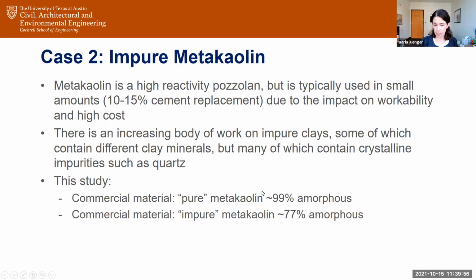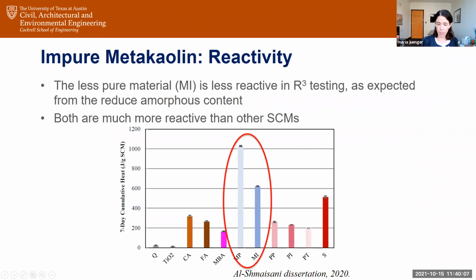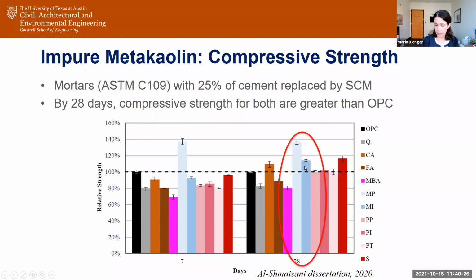So in this particular study, we're comparing a really pure metakaolin clay, a 99%, with one that's more like 77% amorphous and has contaminants in it. And what you can see, if we look at reactivity, the reactivity of both is significantly higher than the fly ash. The reactivity of the less pure material is less than the really good one, but since it's better than the fly ash, it's still suitable for our concrete mixtures. And in terms of compressive strength, the strength is great as well. Reducing the quality doesn't necessarily make it a worse product for our concrete mixtures, and in some cases could actually make it better.